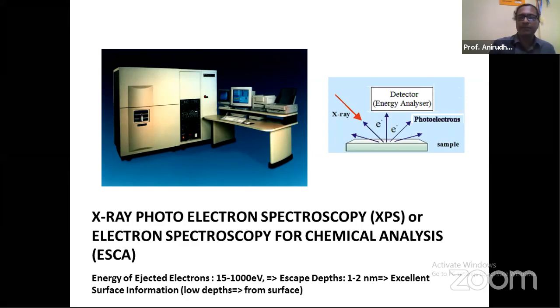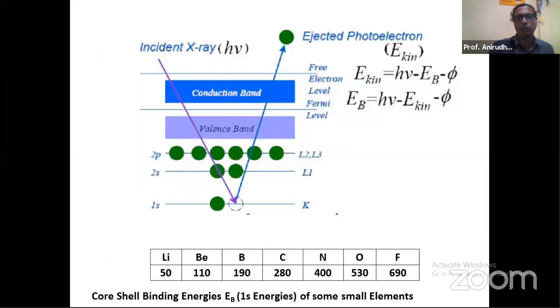Therefore, the information that we are going to get from these photoelectrons using this method is highly representative of the surface and not of the bulk. That means they would provide excellent surface information because they emanate from very low depths, almost from the surface, just 1 to 2 nanometers deep. So this is that equipment.